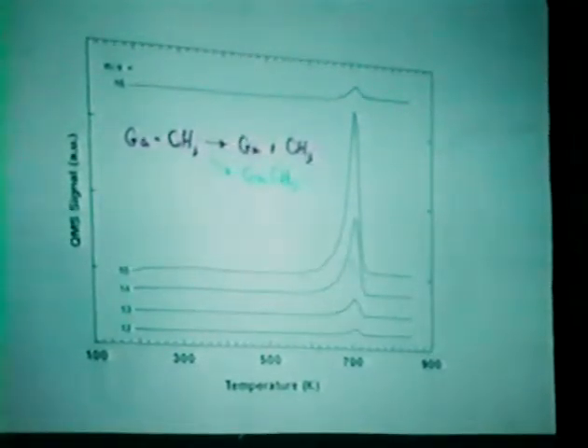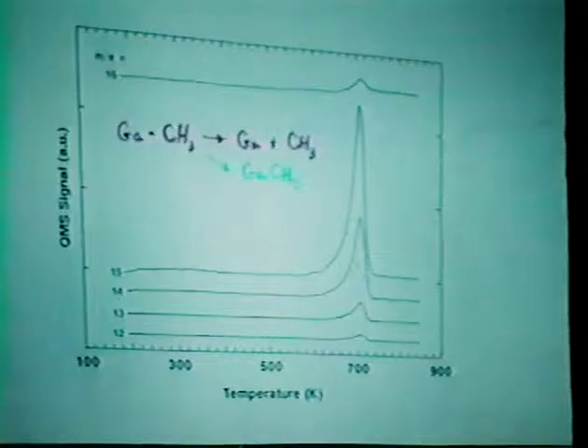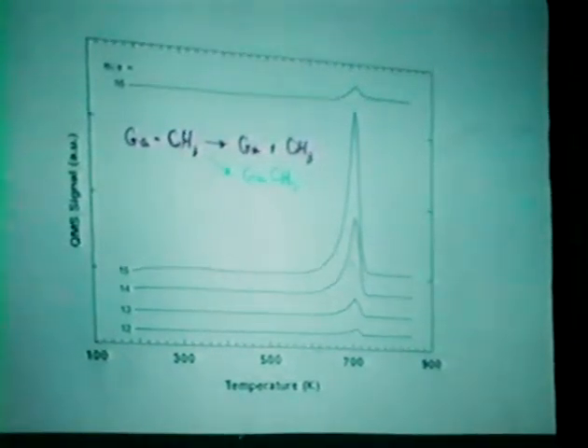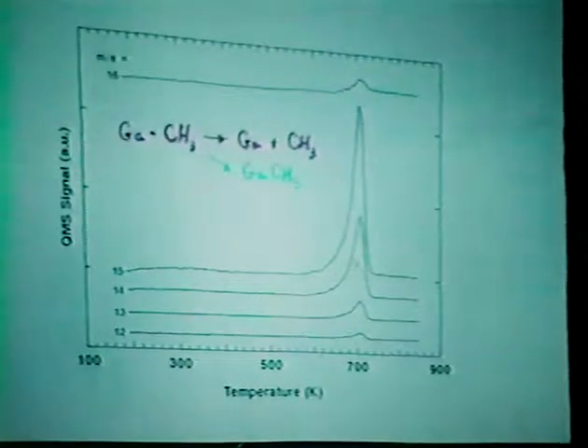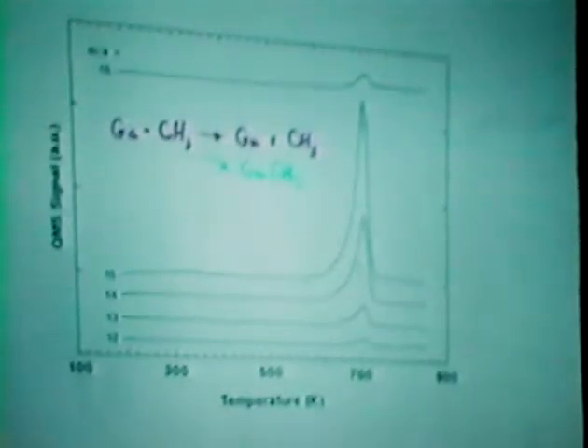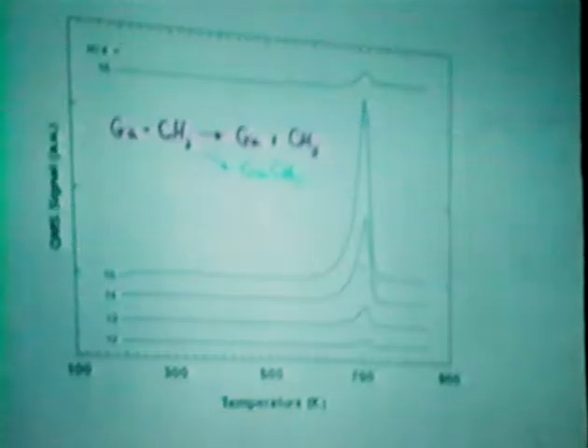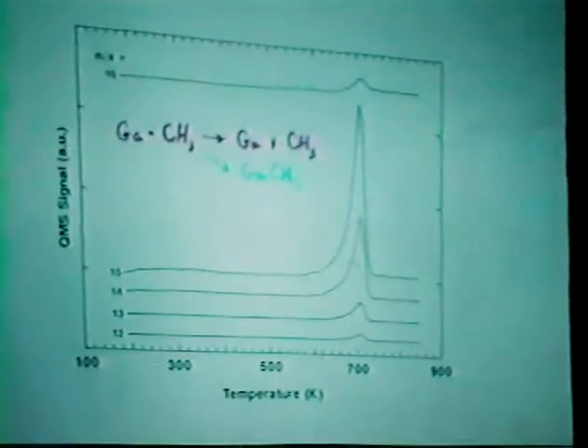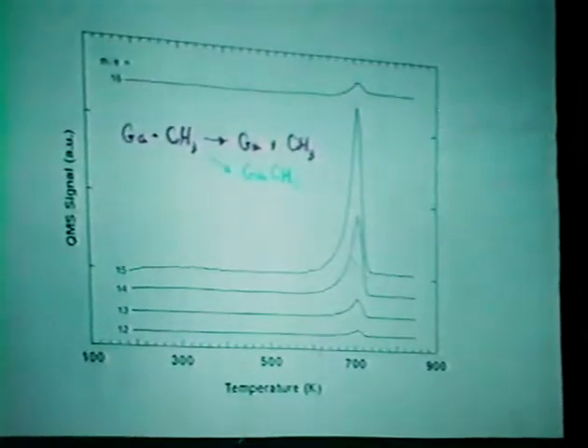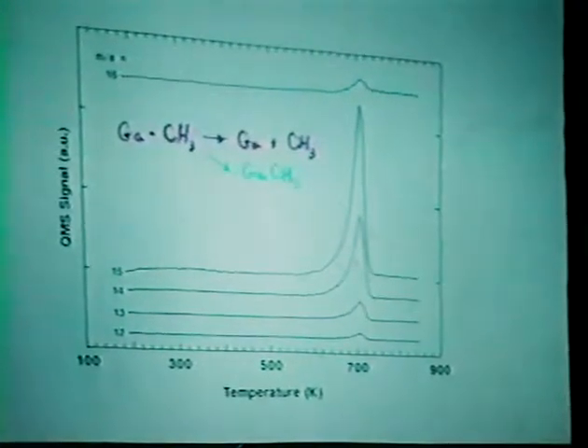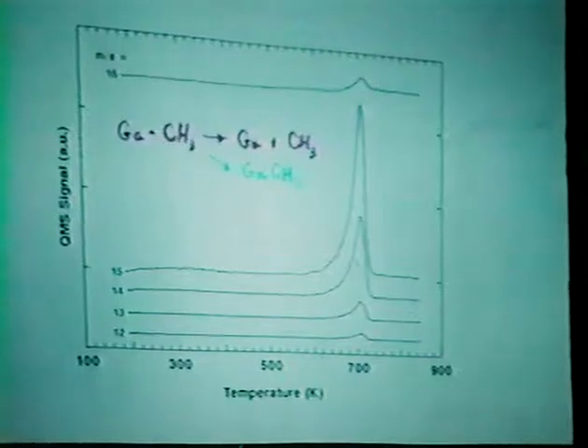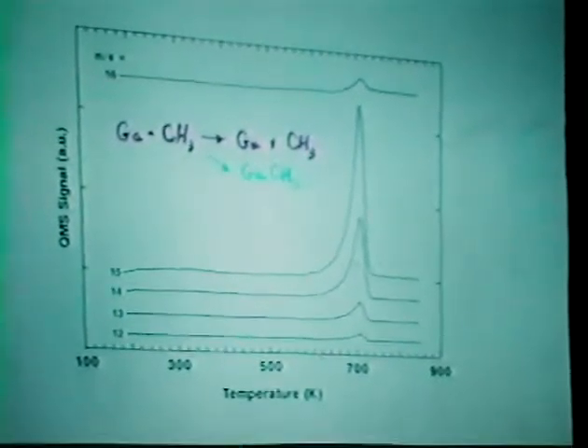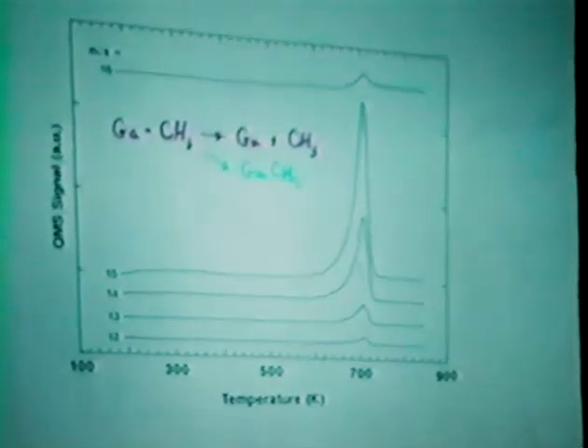And you see that mass 15, 14, 13, and 12, they're at the lower part of the curves, the lower 4 curves, and the upper curve is mass 16. There's no way that that can be methane. Very little methane desorbing here. Then you ask yourself, could that be methyl groups? And the answer is mostly methyl groups desorbing. So methyl groups really do like to desorb as methyl groups from these monomethyl gallium species that we and others believe are important in the decomposition of trimethyl gallium.